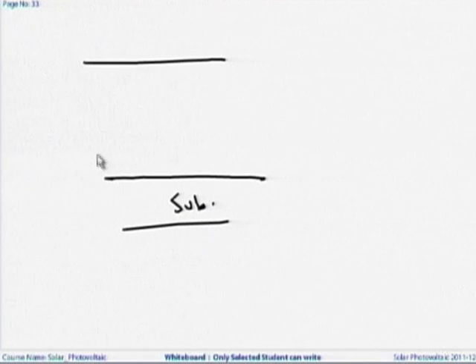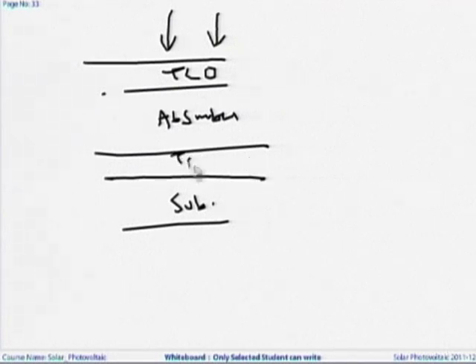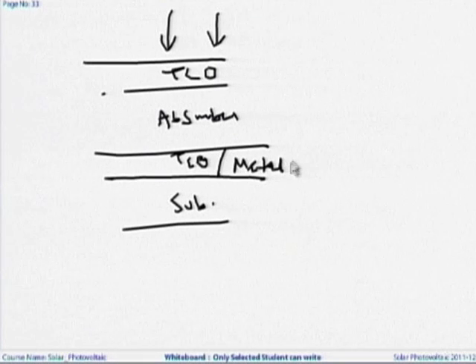For thin film solar cells, you need two electrodes: a front transparent electrode and a back electrode. The back electrode can be TCO or metal such as silver or aluminum. If light comes from the top, the front contact must be transparent. For crystalline silicon, TCO is not used as a front contact because the heavily doped N-type silicon emitter has higher conductivity than TCO, and TCO would cause additional light losses since it is not 100% transparent. The metal finger contact arrangement is the best for crystalline silicon.